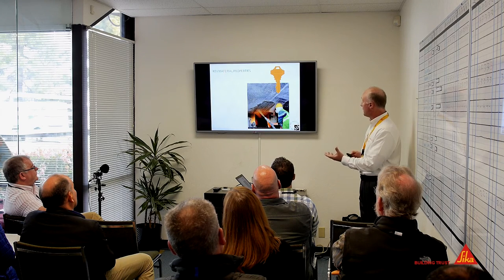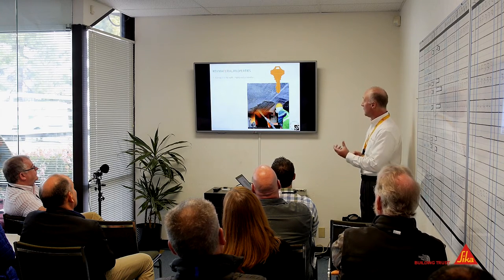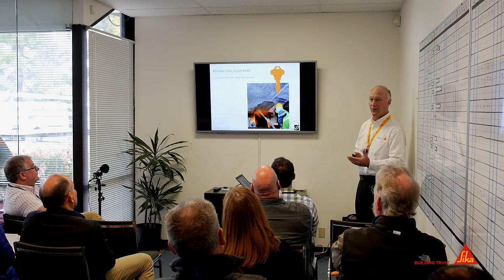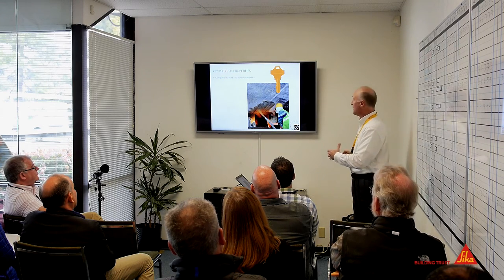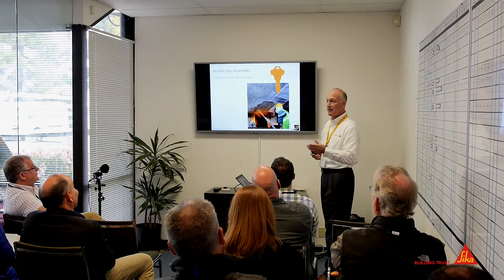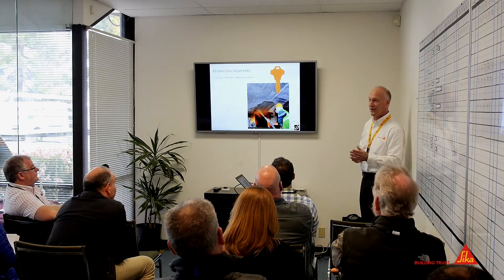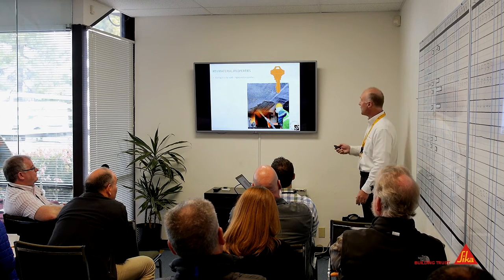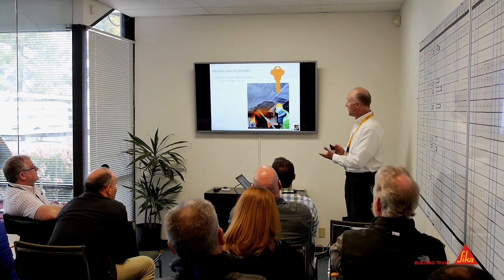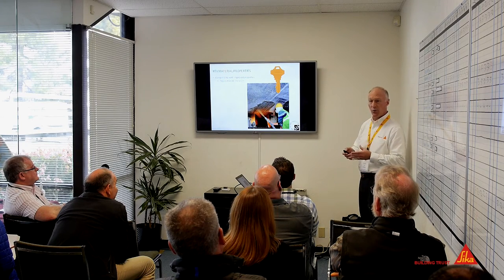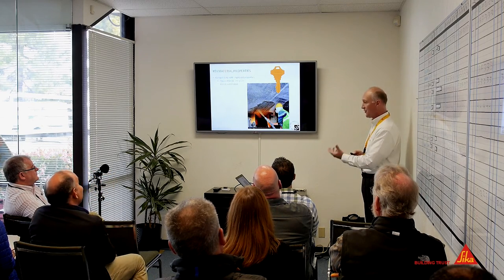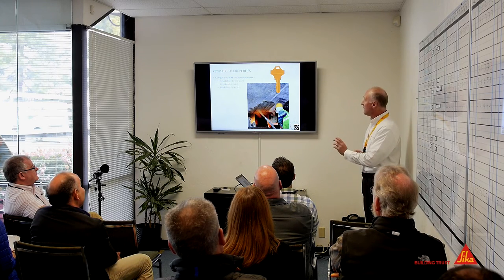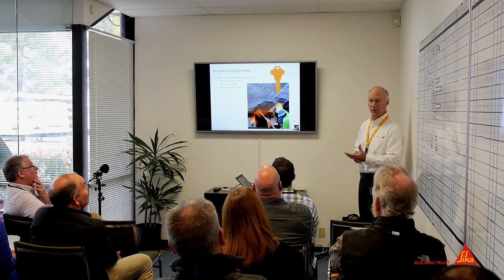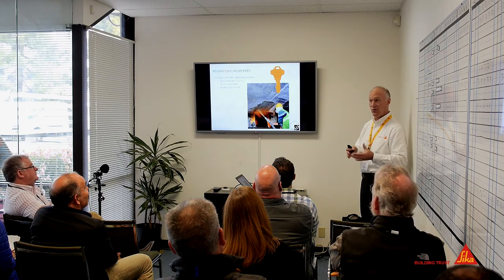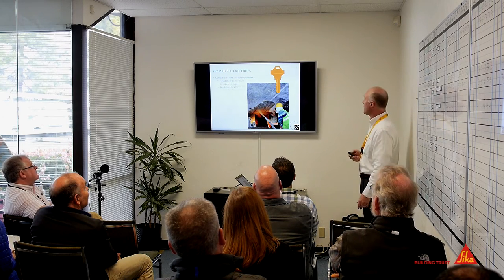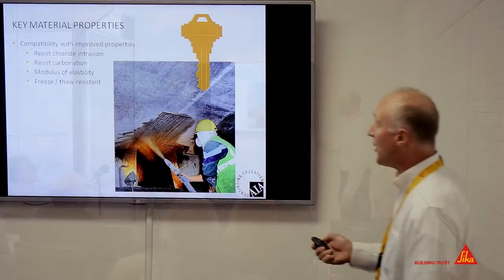So the key properties, whenever we would develop any repair material, we wanted compatibility with improved properties relative to the base concrete. So if my base concrete is 5,000 PSI, I don't need a 10,000 PSI repair material. I need something that's 4 to 6, somewhere in that range. But I do want it to resist chloride intrusion, so I want it to have low permeability. I want it to resist carbonation. I want it to have a modulus of elasticity that's compatible with the substrate, so the way it reacts to potential loads that are placed on it. I want it to resist freeze-thaw.